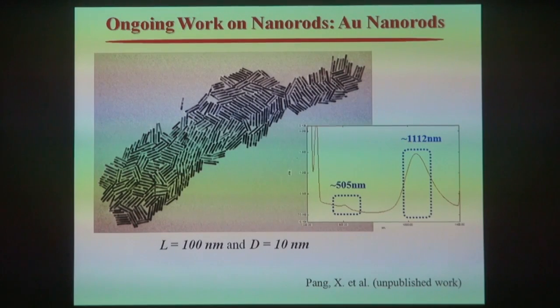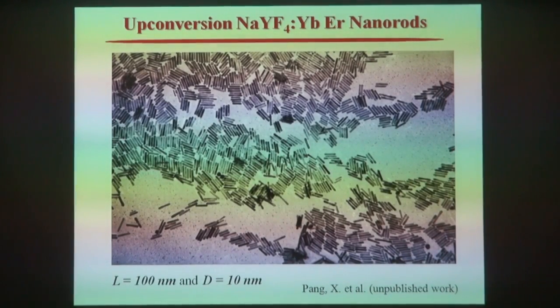So this is gold nanorods. If you switch the precursors to other materials, so this one is if you switch to up-converting materials, that is yttrium, ytterbium, and erbium precursors. If you add these three precursors in the system, you are able to make up-converting sodium yttrium fluoride, ytterbium, erbium nanorods of identical dimension, because the template you are using is the same. They are quite intriguing and can be used in biomedical and also energy-related application, because they can convert the near IR photons into visible.